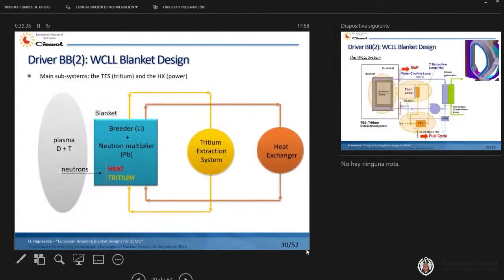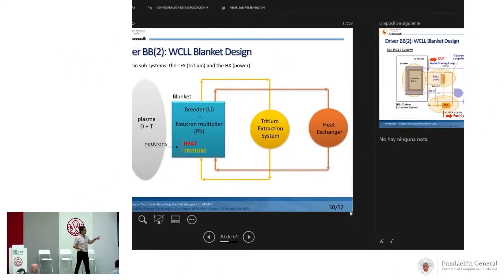Going back to this slide of the main subsystems, in this case the breeder is lithium, the neutron multiplier is lead, and the coolant is water. For the tritium extraction system, we have a dedicated loop of lead lithium. In this case, the lead lithium is the carrier because we produce the tritium in the lead lithium and it goes directly to the tritium extraction system. And the coolant is the water, which goes through this loop to the heat exchanger.